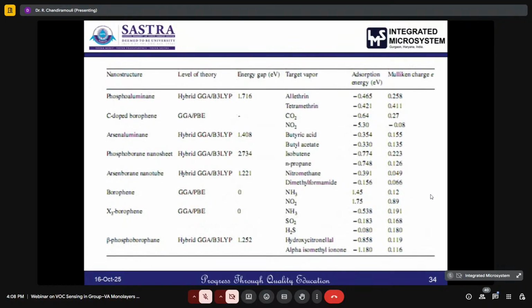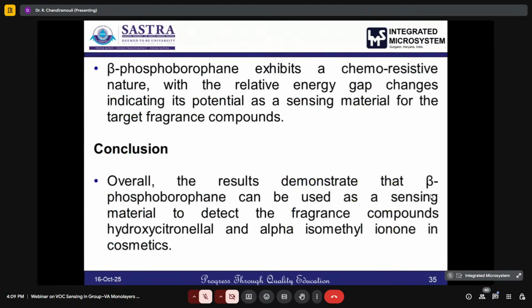And we also made a comparative study of the present work, beta phosphoborophane, with other group 3A, 5A material, phosphoaluminene. That is also being reported by our group. Depending upon the different levels of theory, we also obtained the energy gap, and the target vapor is also listed here, and the adsorption energy and Mulliken charge are also reported here. And the beta phosphoborophane exhibits a chemoresistive nature if you use it as a two-probe device. Whenever there is an adsorption and desorption of the target vapor, a change in the resistance is noticed, so it can exhibit a chemoresistive nature with the relative energy gap changes, indicating its potential application as sensing material for the target fragrance compound.